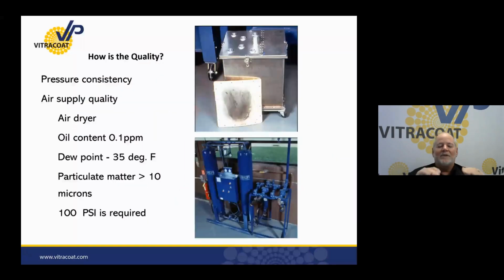I don't know how many times I've seen a plenum plate on a fluidized bed that looks like this upper right-hand picture, where oil has gotten through and plugged that plenum. Quality of air is critical. It should have a dew point of minus 35 degrees, oil content very, very low, negligible to zero. We've got to take out all particulate matter greater than 10 micron. And I have to have 100 PSI. I'm not going to run my guns at 100 PSI typically, but I need 100 PSI.